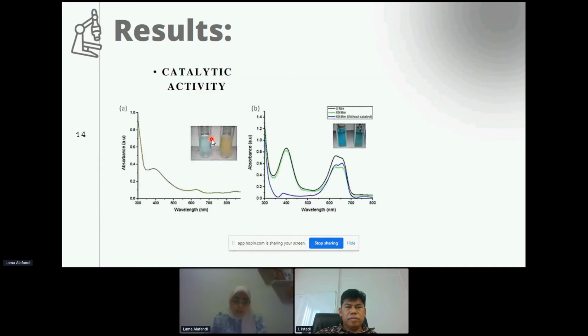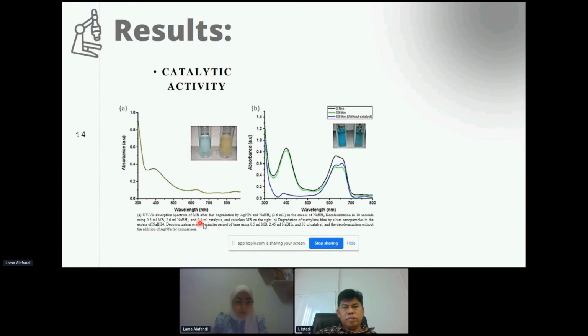Lastly, the catalytic activity. After we obtained the silver nanoparticles, they were tested as a catalyst to reduce methylene blue. First, we started with 0.5 milli of catalyst, and that caused the reaction to be very fast. Within 10 seconds, we got this flat curve, and the solution turned yellow. Therefore, some parameters in the experiment were adjusted, such as the amount of the catalyst.